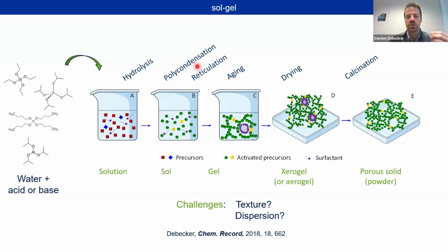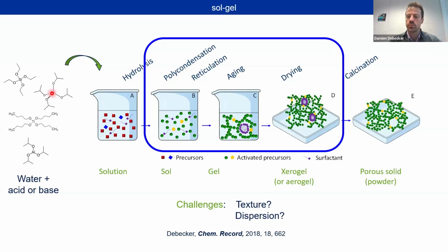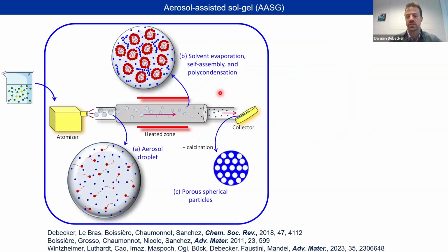One big challenge in sol gel chemistry is that those precursors will not react at the same pace. And so what you end up is very often inhomogeneous solids with, for example, if those react too fast, you might have an island of titania in an ocean of silica instead of having isolated titanium sites in your silica. So that's a challenge, and it's related to the fact that you work in water under slow reaction conditions, but some of them react way too fast. So doing this in the aerosol allows you to solve these problems even better, because all these steps that I have highlighted here, we will do them in a matter of seconds, 1 second, 2 seconds.